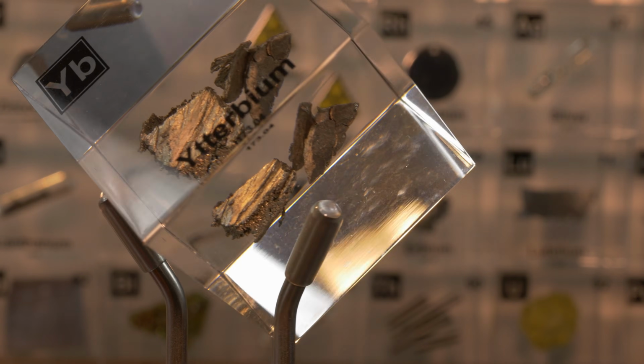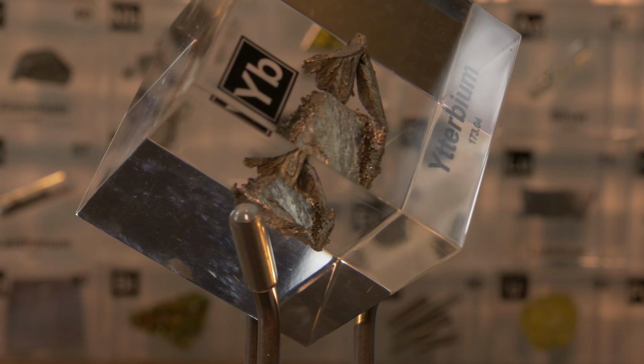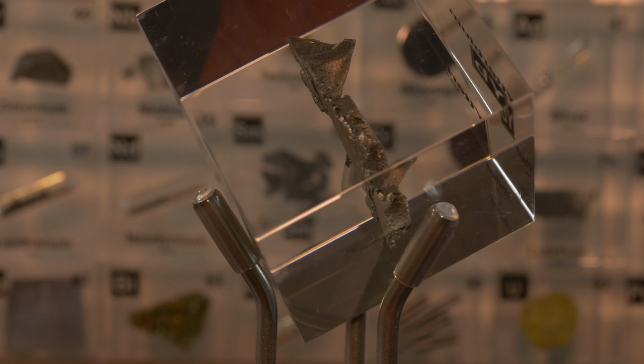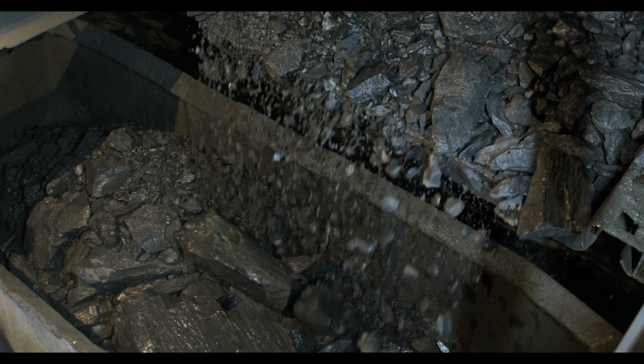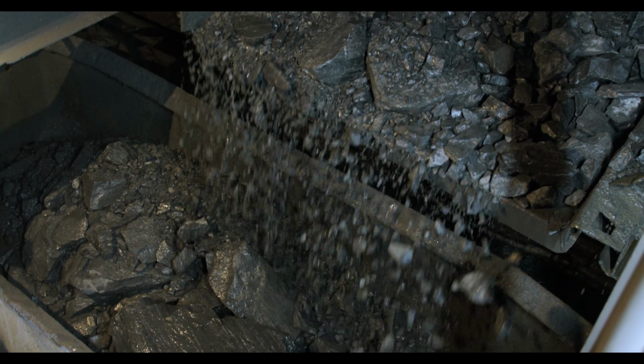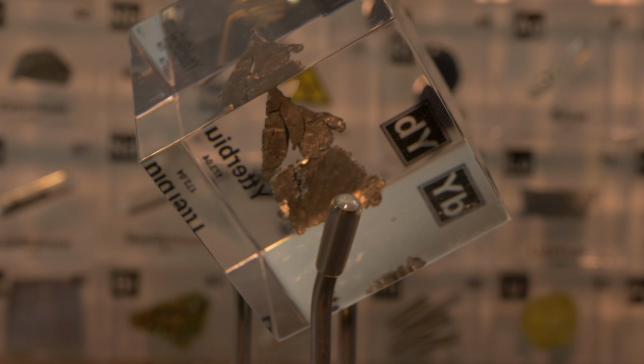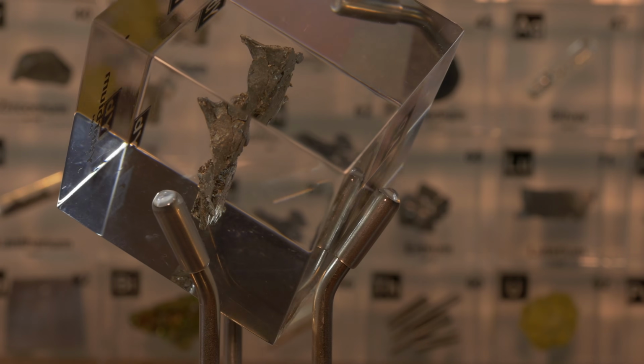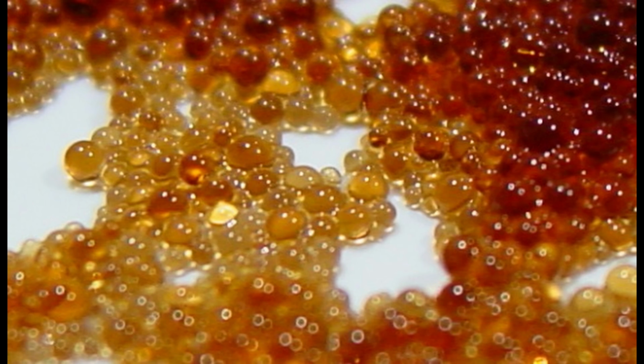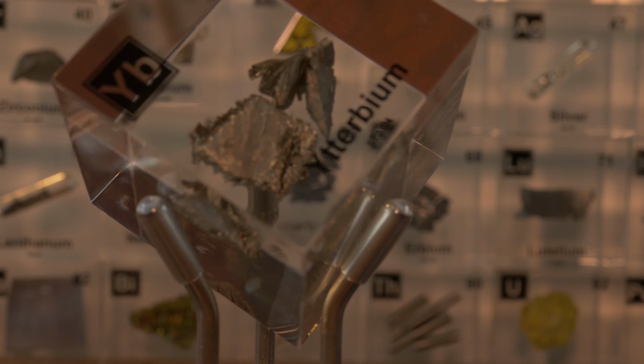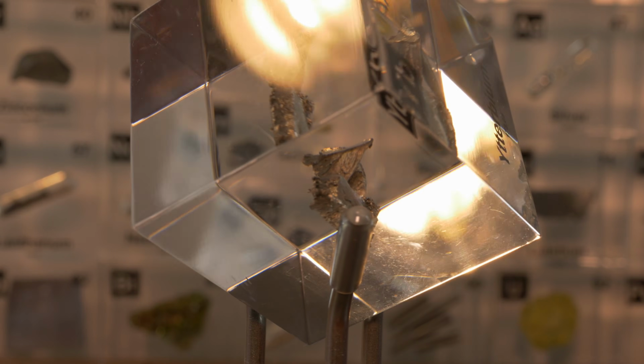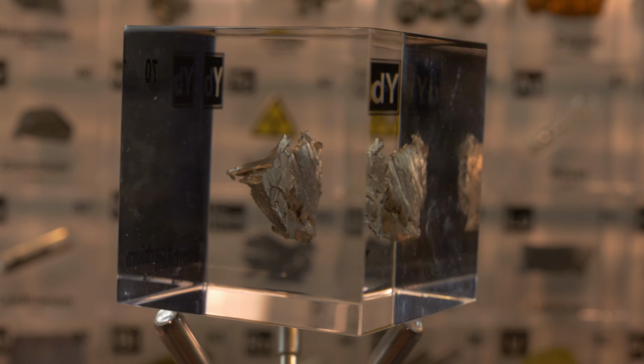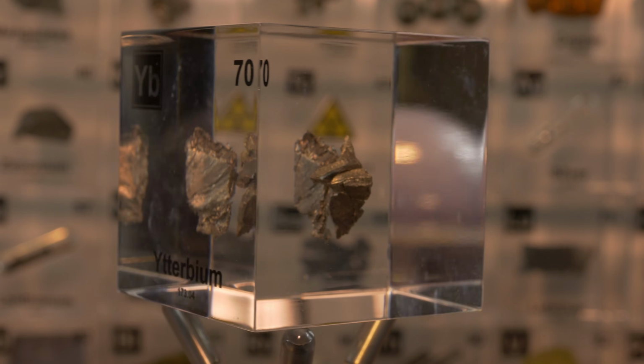Now, getting pure ytterbium is not as simple as digging up a shiny nugget. Like most rare earth elements, ytterbium hides inside minerals such as monazite and xenotime, where it's mixed with other lanthanides. To separate it, miners first crush the ore and then treat it with strong acids or hot alkalis, which dissolve the rare earth elements into a complex soup of ions. The tricky part is pulling them apart, since lanthanides behave almost the same chemically. Modern industries use solvent extraction, where organic liquids selectively grab one element at a time, or ion exchange resins, which act like molecular sieves. Because ytterbium can exist in a rare +2 state, as well as the usual +3, chemists also used selective reduction methods, such as reacting it with sodium amalgam to isolate it from its neighbors. Once separated, ytterbium is usually converted into compounds like ytterbium oxide or ytterbium chloride.